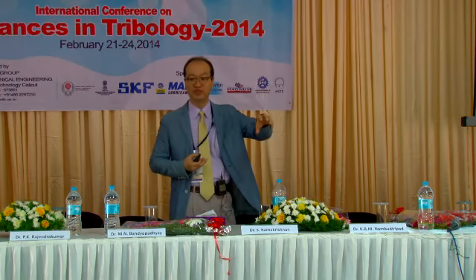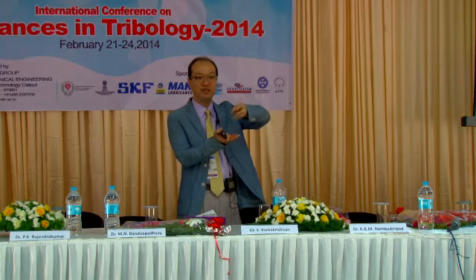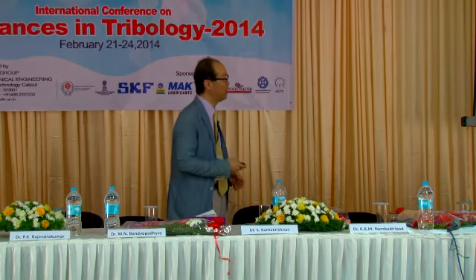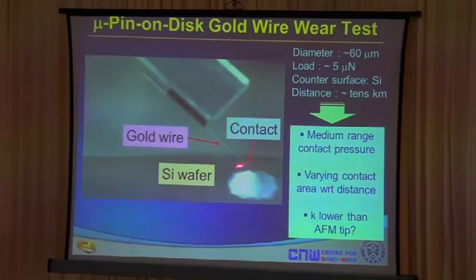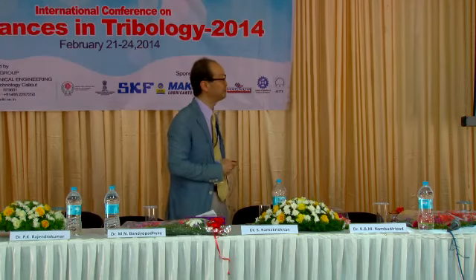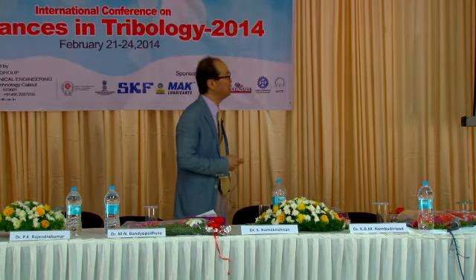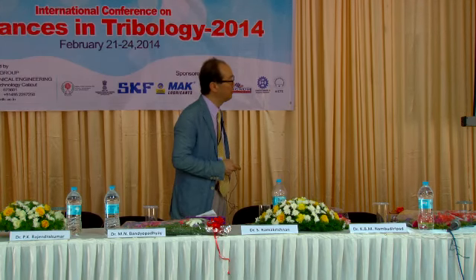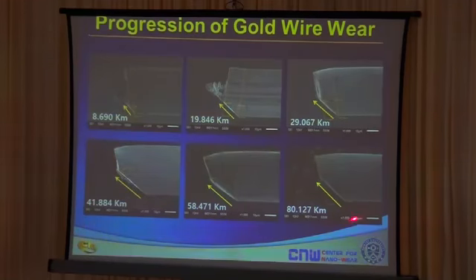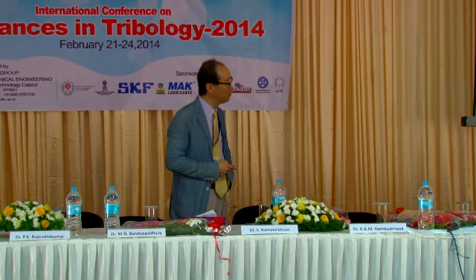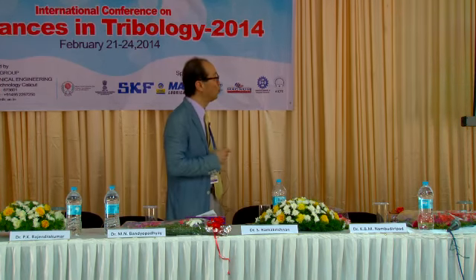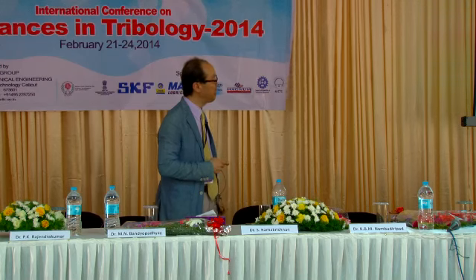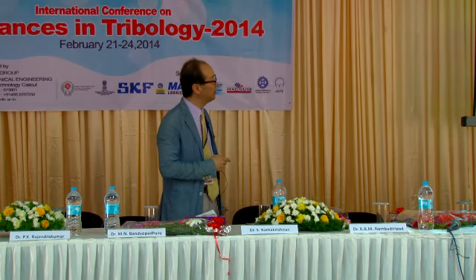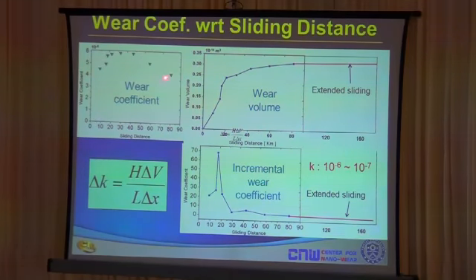So the wire is in the form of a cylinder, and basically what you're doing is you're contacting the edge against the silicon wafer. And we're rotating the silicon wafer to create a wear on the tip of the gold wire. This is the amount of wear you get after 29, 58, and 80 kilometers of sliding. And the amount of wear we can quantify is by noting the volume that's been taken out from this tip of the gold wire. And when we quantify this, what we find is that the wear coefficient varies with sliding distance. It does not increase continuously. It increases and starts to go down.